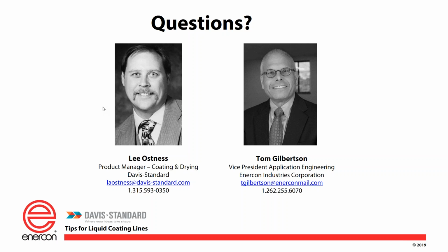Lee, we have a question on how does drying and curing dwell time compare between UV cured coatings and water-based coatings? A UV cured coating is determined by the amount of initiator that's added to the formulations that you put into it. So let's say if I were to take a water-based silicone versus a UV 100% solid silicone, they're not even comparable in this realm. A water-based, you have to get rid of the solution water and then hit it with a temperature to cure it, and it takes so much time at a temperature. Whereas a UV, it takes a certain power from that wavelength of light to initiate that chemical. And the more power you have in the light, or the more initiator, cuts down the amount of time.